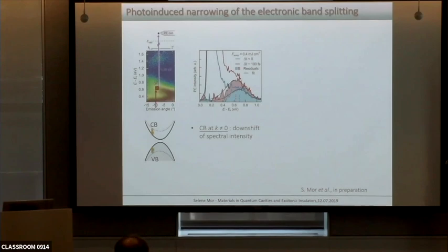So therefore, from the ratio of those two things, you get the EI's V, the excitonic insulator interaction energy. There should be almost a direct one-to-one relation within some theory, because the whole point of the V is this. But are you referring to reduction of the band with temperature? No, with excitation.